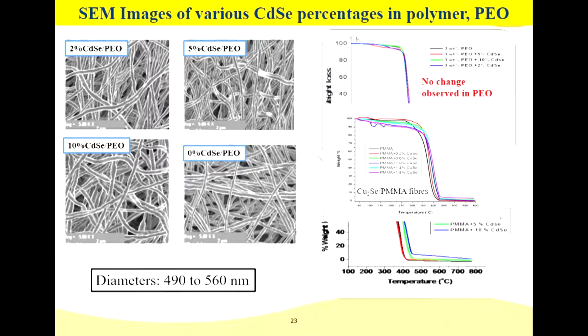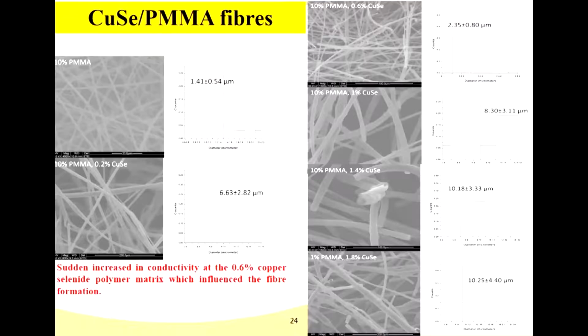This also shows when you're adding your copper selenide into the same PMMA, which shows some variable change in the thermal stability. The other thing that we tried to explore was, since you're adding this copper selenide and these nanomaterials into the polymer fibers, what is happening in terms of their conductivity?